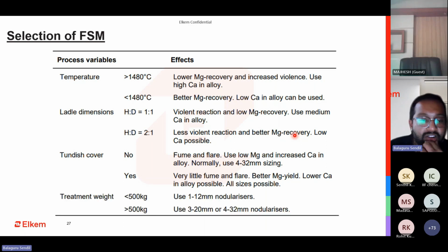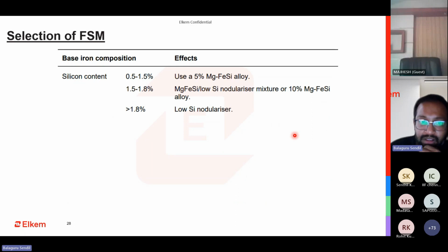And the last one is the treatment size. If it is less than 500 kgs, you can go for 1 to 12 mm, which is the most common size. If it is greater than 500, these are the sizes we use globally in Elkem. In India, we do a lot of customizing of sizes because of the mindset and the ladles we have seen, but we are trying to slowly change it. So these are the process variables that you have to take into consideration: your temperature, your ladle, your tundish, and your treatment weight. On the chemistry part, the first thing is your silicon content.